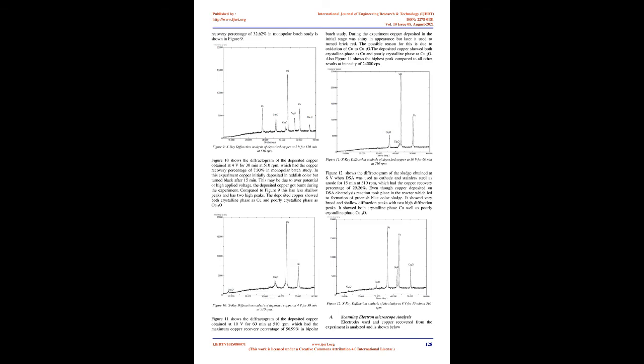Effect of supporting electrolyte. Supporting electrolytes are widely used in electrochemical measurements when control of electrode potentials is required. This is done to increase the conductivity of the solution. Experiments were conducted in order to investigate the effect of the supporting electrolyte. Sodium chloride, NaCl, was used as supporting electrolyte. Experiment was conducted in bipolar arrangement using 4 stainless steel at 10V for 60 minutes at 300 rpm.